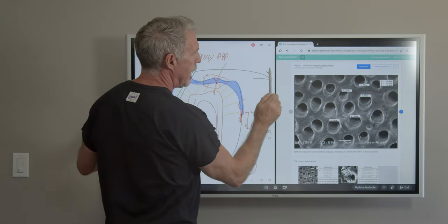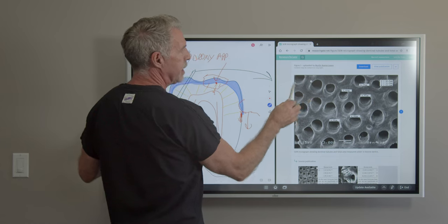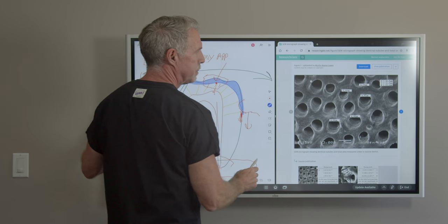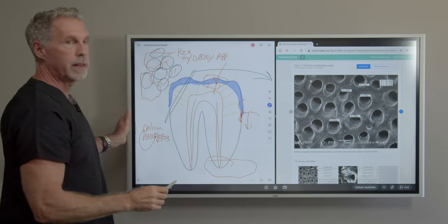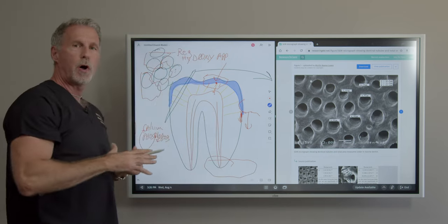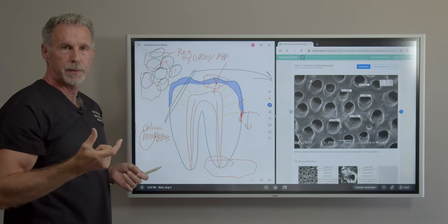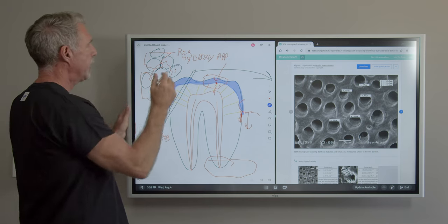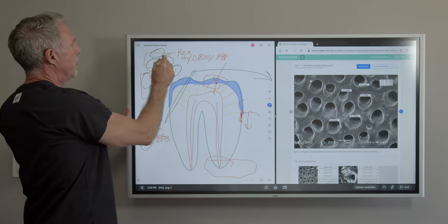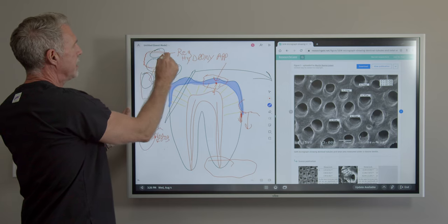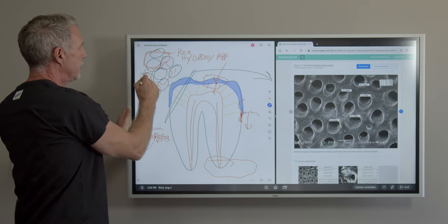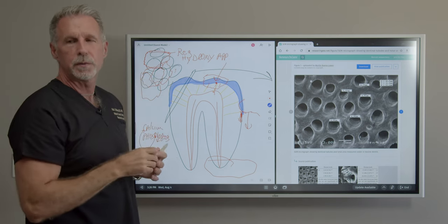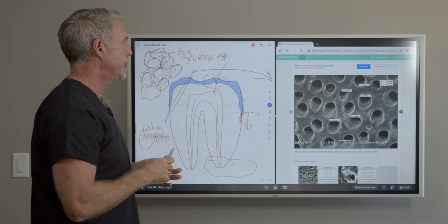So over here with the hydroxyapatite, the concept is that by brushing and putting hydroxyapatite, it will seal these tubules. And in theory, it should work, but if you're not using a small or nano-hydroxyapatite, nano meaning very small size particle, if using a regular size hydroxyapatite, those pieces are about this big in scale to the dentinal tubules. So they might try to lay over, but they're not going to go inside the dentinal tubules, and we want them to go inside the dentinal tubules.